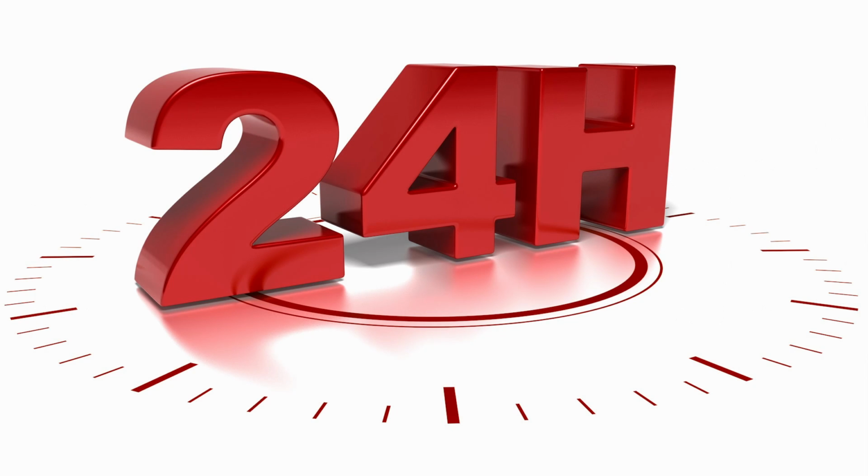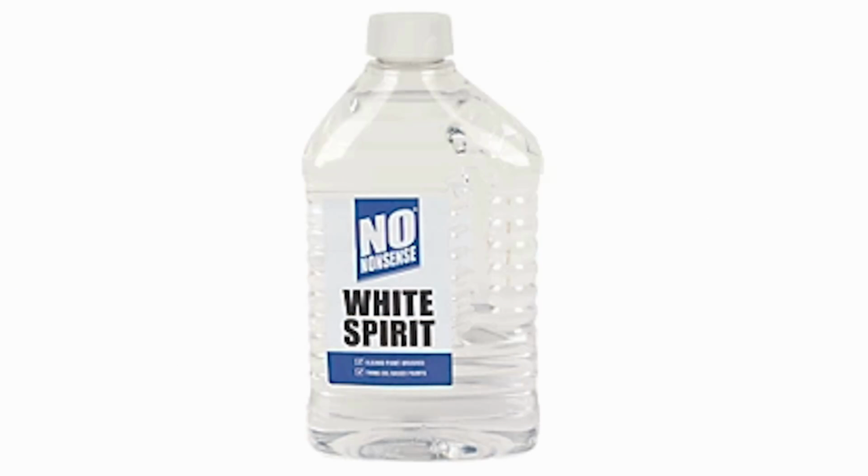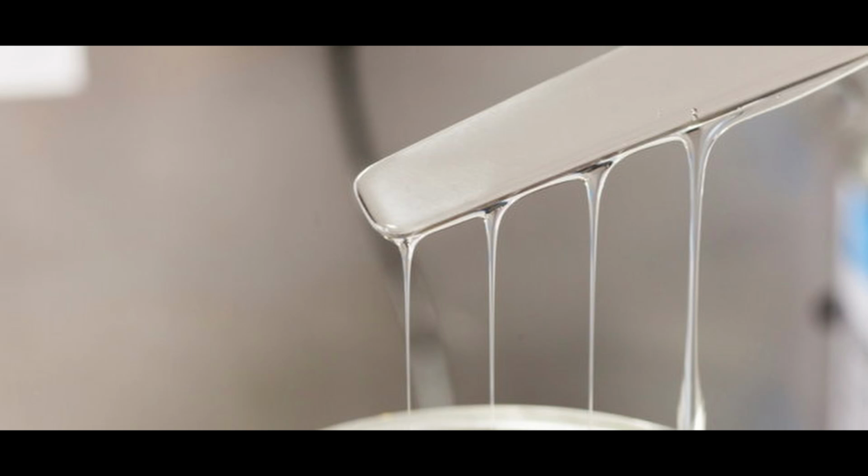Alkyd paints then took that linseed oil and chemically modified it to create a resin, something that would polymerize faster than the oil itself, and we have the polyester binders that are the backbone of enamel paints, but the solvents are still mineral spirit based. In acrylic paints, the binder is acrylic, which also polymerizes to create a hard, resistant finish.